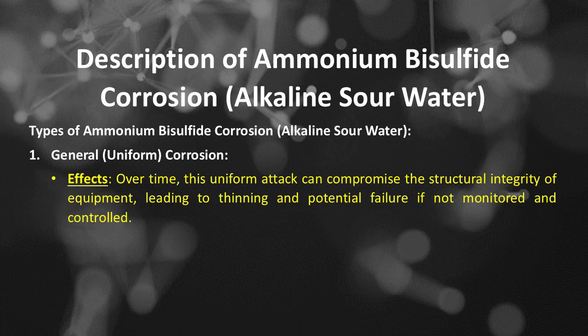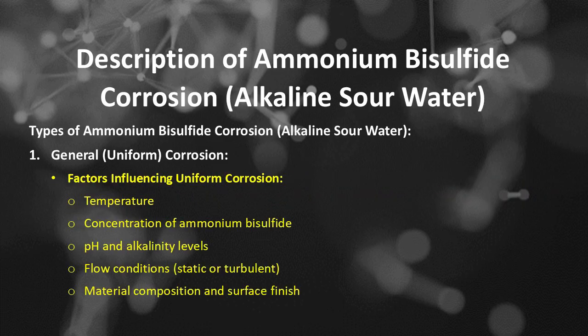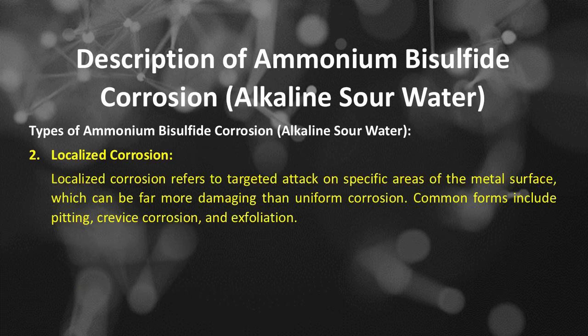monitored and controlled. Factors influencing uniform corrosion include temperature, concentration of ammonium bisulfide, pH and alkalinity levels, flow conditions, static or turbulent, material composition and surface finish. Number 2 of the types of ammonium bisulfide corrosion or alkaline sour water is localized corrosion. Localized corrosion refers to targeted attack on specific areas of the metal surface, which can be far more damaging than uniform corrosion. Common forms include pitting, crevice corrosion, and exfoliation.